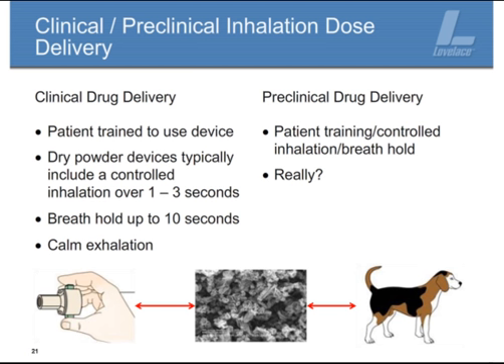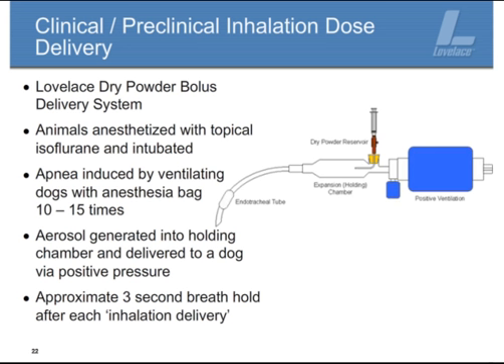So what I'd like to start out with talking about is how the team at Lovelace, many years ago, in fact working on Exubera, developed methods to try to mimic a clinical maneuver so we could take well-engineered dry powder formulations like the material that Bend Research develops and transition them into a clinically relevant preclinical model. In doing that, we developed a system here at Lovelace that we've called the dry powder bolus delivery system. If you look at the image on the right, this system consists of a dry powder reservoir, an expansion holding chamber, and an endotracheal tube.